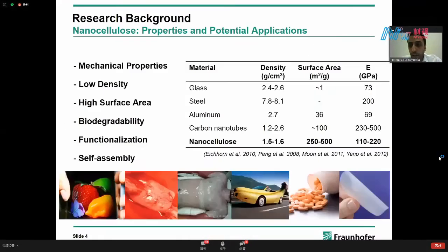Now, why is nanocellulose in general interesting? Because of the many properties nanocellulose has. Some of these properties nanocellulose has inherited from cellulose itself, such as biodegradability and low density. But nanocellulose also has high mechanical properties, around 100 to 200 gigapascal, we're talking about Young's modulus here, which is pretty comparable to carbon nanotubes and steel, with a pretty low density of around 1.5 gram per cubic centimeter, it's even actually lower than that.